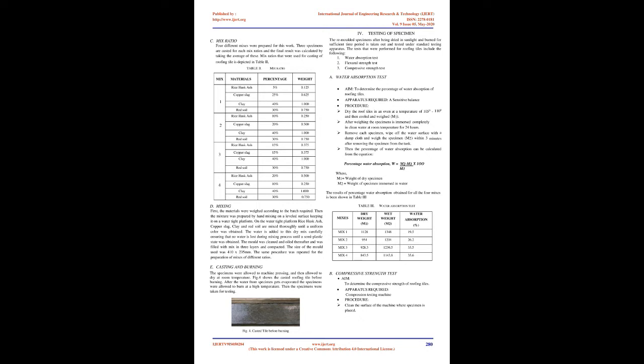Casting and burning. The specimens were subjected to machine pressing, and then allowed to dry at room temperature. Fig. 4 shows the casted roofing tile before burning. After the water from the specimens evaporated, the specimens were burned at a high temperature. Then the specimens were taken for testing.